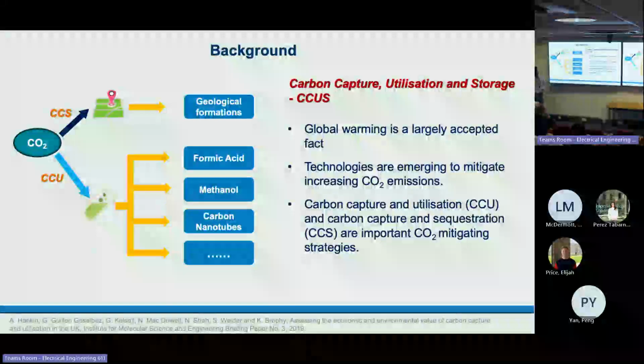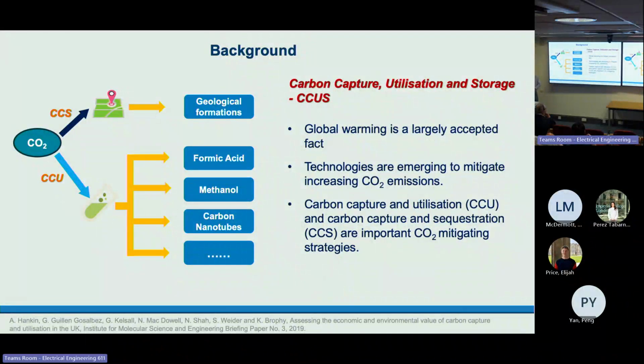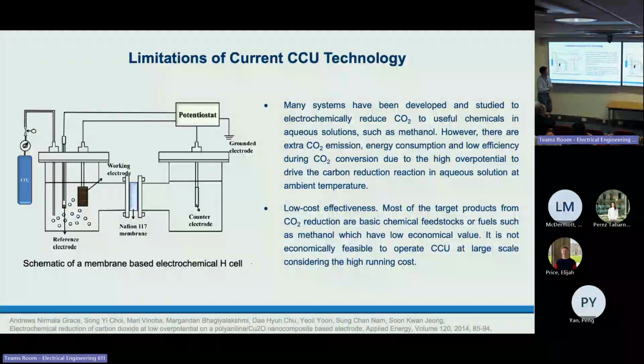It's a very good strategy, but there are some problems with current CCU technologies. There are many systems which have been developed and studied to electrochemically reduce CO2 into useful chemicals in aqueous solution, such as methanol. However, there are extra CO2 emission and energy consumption, and the efficiency is quite low during the conversion process because of the high overpotential to drive the carbon reduction reaction in aqueous solution at low ambient